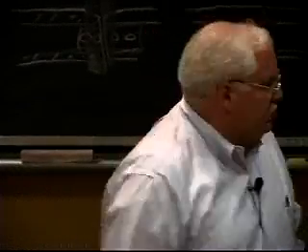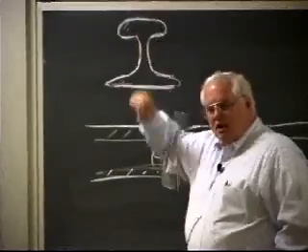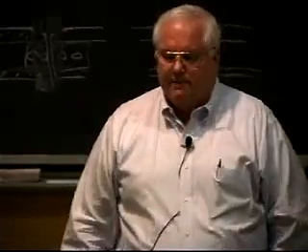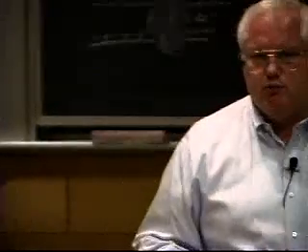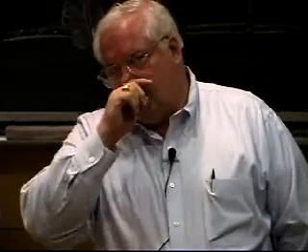But since most of the stress is right on the head, all you really care about is making sure you get a good weld up here. And sometimes they go in with ultrasonics afterwards to make sure they get a good weld, okay? You can go with stick electrode, but it's a very slow process. You have to preheat these types of steels to like 500-600 degrees Fahrenheit, so the guy is working next to an oven. It's not a very pleasant process. So stick welds, I've seen them in rails, but they're usually lousy.